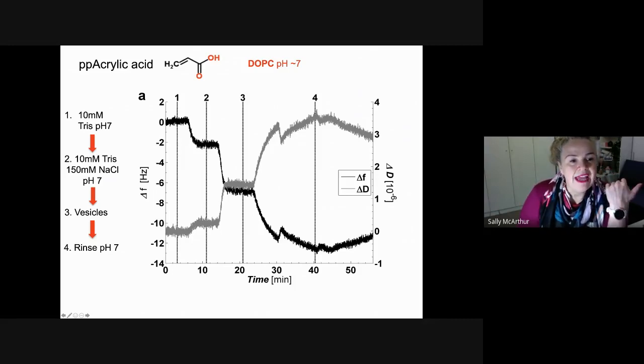When we add in sodium chloride into the system, you can see we get a bit more swelling as well, and we get a dissipation change that tells us the layer has become slightly more viscoelastic. It's now not just a rigid layer, it's actually done a bit of swelling. And then at this point 3, we add the vesicles, and you can see we get a little bit of adsorption and a little bit of a dissipation rise. These units are actually very small. Okay, so they're very small amounts of adsorption.